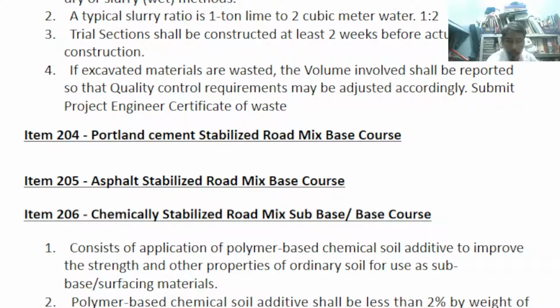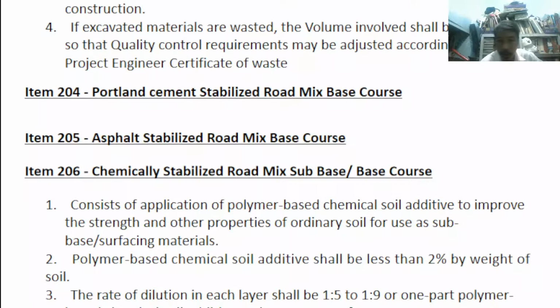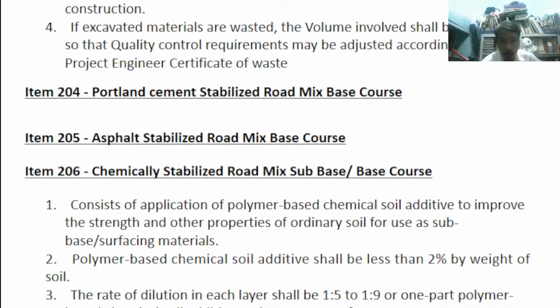And number 3, the rate of dilution of each layer shall be 1:5 to 1:9, or 1 part polymer and 5 to 9 parts of water.